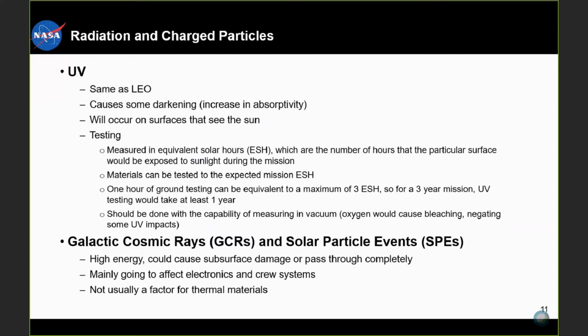But Gateway's mission lifetime is 15 years. So if we wanted to do the full UV testing for Gateway, it would be 5 years of testing. An important thing that we should know about UV testing is that it really should be done with the capability of measuring in vacuum, because exposure to oxygen causes bleaching, which negates some of the UV impacts. So you're not really measuring the same thing. And that's especially important for NRHO, because we don't have oxygen out there.